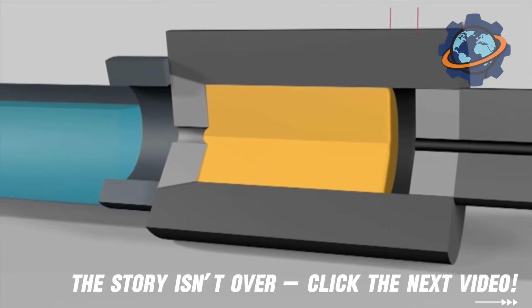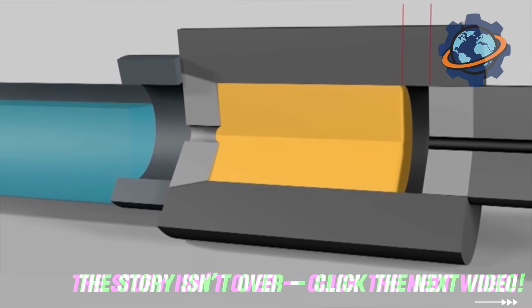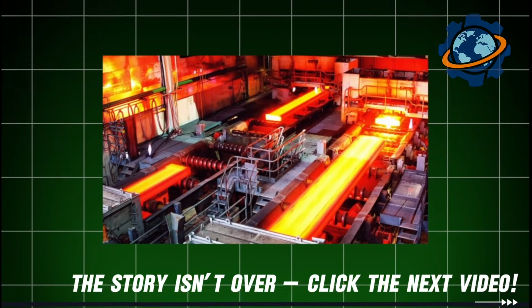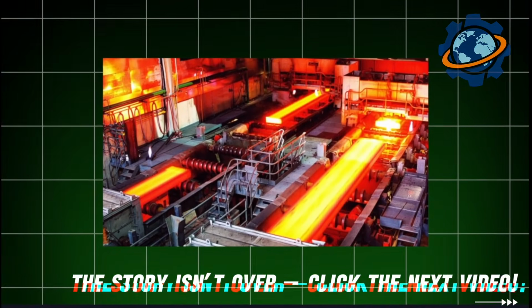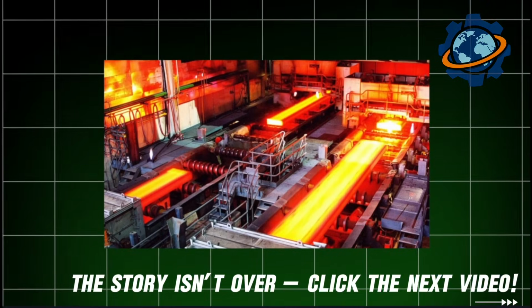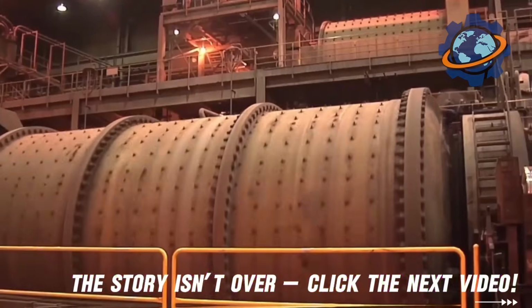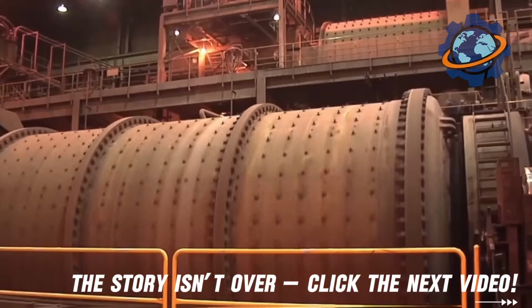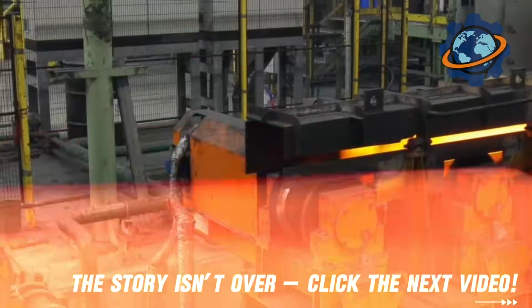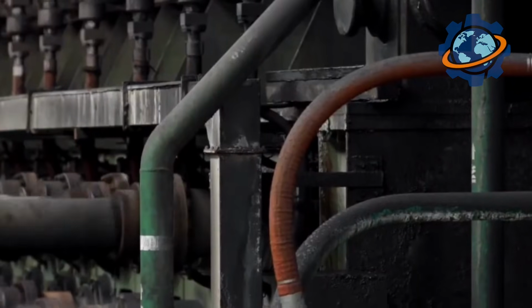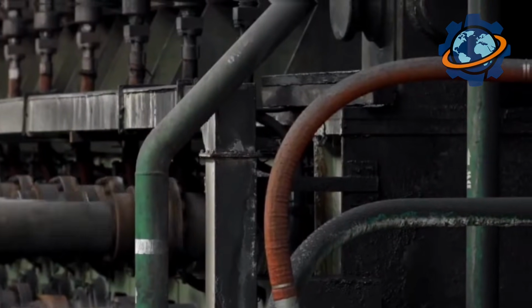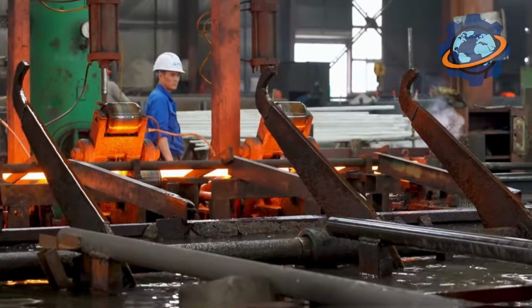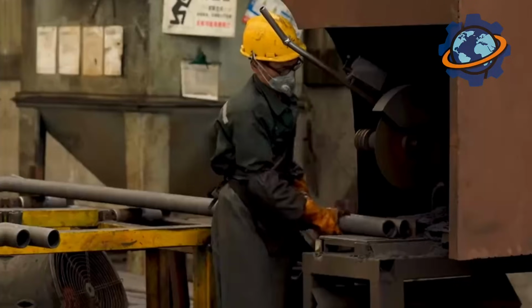The slab gets thinner and longer. It passes through the next pair of rolls, even thinner, dozens of times. An 8-inch thick slab becomes a sheet 1 to 2 millimeters thick. Length grows from 33 feet to over half a mile. Rolling speed on finishing mills reaches 50 miles per hour. Red-hot steel ribbon flies through the mill, sparks flying everywhere.